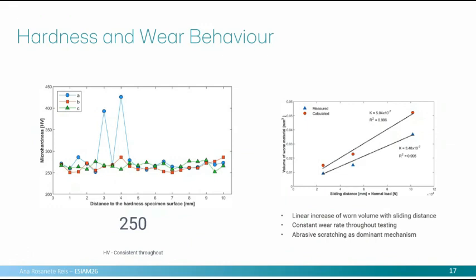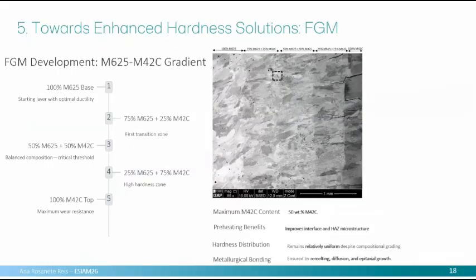As expected, the wear behavior was not so good. So then we thought, why don't we mix the two materials, and try to see if we get an improvement in hardness. We did it like we show here. We tried 100% Inconel at the base, then started adding a little bit of Metco, the hard material, and then went until the final layer was totally the hard material. The conclusion is that after 50% we don't get good depositions, you get cracks. So we understood that this is the maximum content that we could use.